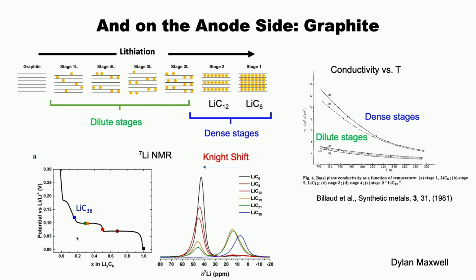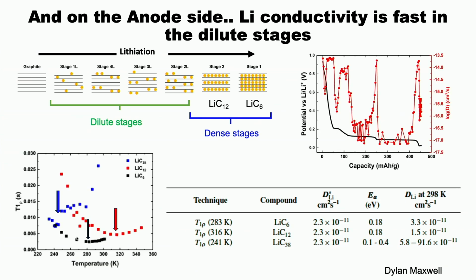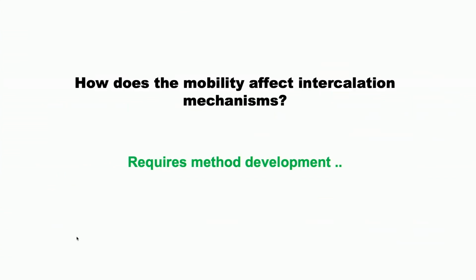And then the other thing that's interesting about it, that again comes out from the NMR, is via a technique called a T1 rho measurement, you can quantify the diffusivity. And it's very easy to get the diffusion coefficient at the so-called T1 minimum. And so the minimum is where the transport is the same frequency as the Larmor frequency. And so as you go from a dilute stage to stage 1, you can see that the diffusivity here is the same, but the temperature at which you achieve that diffusion coefficient varies. And so the diffusion coefficients in the dilute stages are much faster than in the dense stages. But they're of the order of 10 to the minus 11 centimeters squared per second.